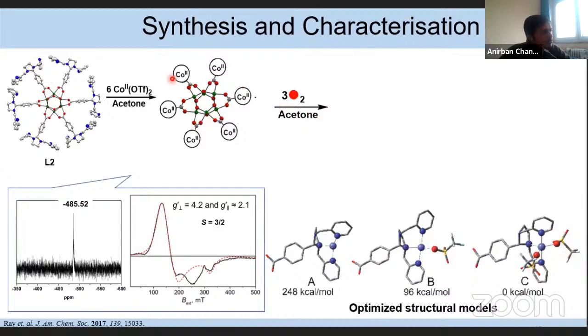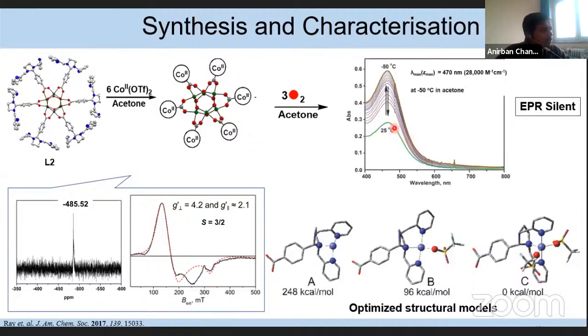And upon oxygenation of this cobalt-6 complex, we get one UV-vis absorption band at 470 nanometer. So going from tetranuclear to hexanuclear, the UV-vis absorption band shifts about 6 nanometer, but the molar extinction coefficient value is around 28,000. Maybe it's because of the higher number of metal centers involved in this hexanuclear species. The formation of this new species also depends on the temperature, and it's a reversible process. The newly formed species is EPR silent.